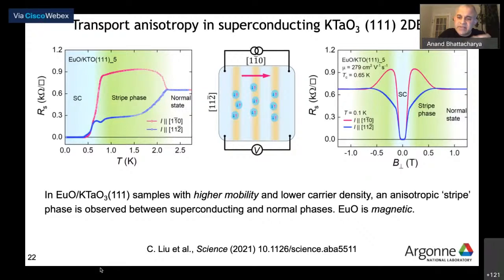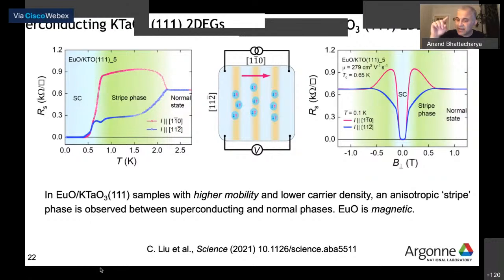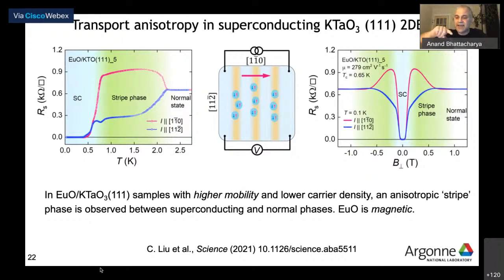And if you start at a low temperature, like 0.1 Kelvin, and you apply a magnetic field, what you find is that the resistance will rise in both directions, for currents along both directions, but they'll behave very differently as they approach the normal state. In one case, for the hard direction, it'll go up to a high value, higher than the normal state, and come down again. In the other direction, it rises up, then flattens out. It has an almost linear slope, actually, which should tell you kind of what it might be. And then it flattens out again.